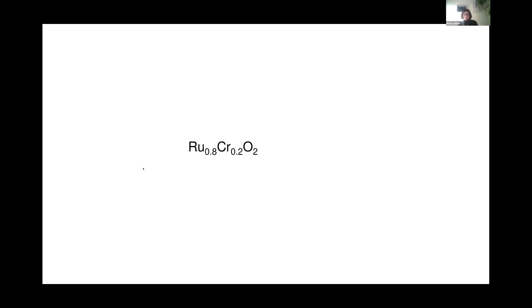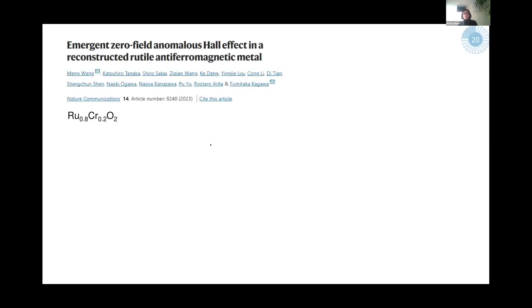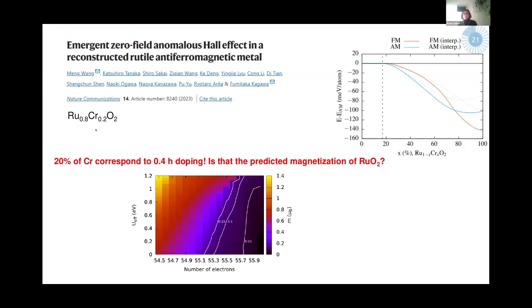And this is, in fact, results by Andriy and Igor. There is this material where there was recently this work where they were claiming that they were finding an emergent, now zero field, so not defined, but zero field anomalous Hall effect in this material. So in ruthenium oxide doped with chromium. And when one looks at this formula, the system that they seem to have has 20% of chromium, which would correspond to 0.4 holes doping.